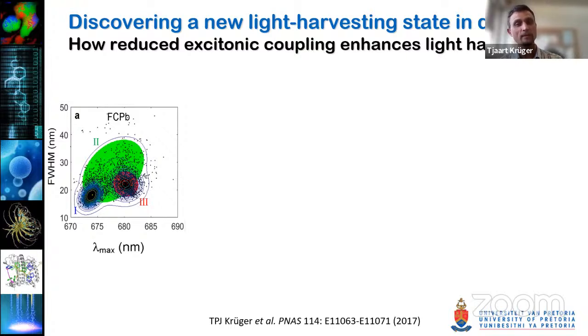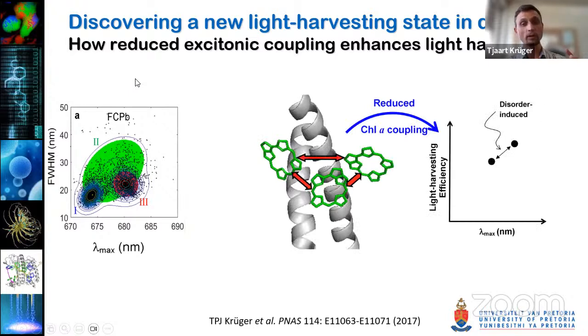So one would expect that when enhancing the excitonic coupling, that would also enhance the light harvesting function of these systems. But now we've identified a new light harvesting state. The reduced excitonic coupling makes provision for new light harvesting states, actually 2 new states to form, which we have identified. And we have also modeled this system. The only way that you can explain these new spectroscopic states is when there is reduced chlorophyll A coupling.